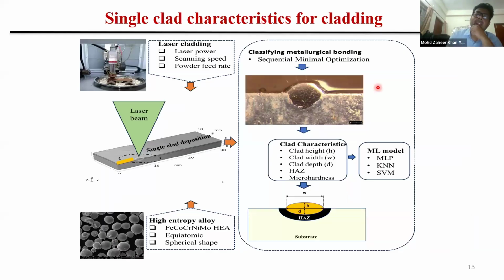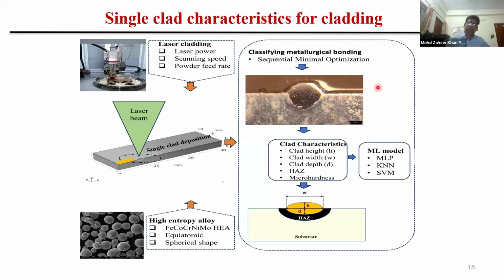So, before any such experiment is performed, a single clad characteristic of the cladding has to be obtained. For this, a series of experiments were performed. In this series of experiments, we took a chosen powder, and we just made one single bead using the powder that is being used. So the laser head was moved on a plate from one end to the other end of the length of the plate, and a single bead was obtained.